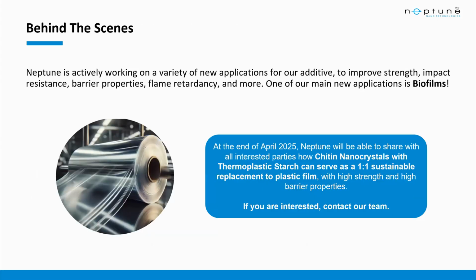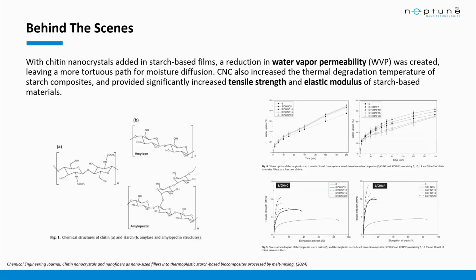And beyond just paper packaging, chitin nanocrystal works for plastic packaging as well. In fact, as of right now, we're developing a fully biodegradable thermoplastic film packaging. It's based on thermoplastic starch and it's enhanced with chitin nanocrystals. We're already observing large uplift in strength as well as barrier properties. We're seeing some really good lab scale results due to a natural compatibility between chitin and starch. We're observing the tensile strength of the starch more than double thanks to the addition of chitin nanocrystals, and this goes for barrier properties as well.